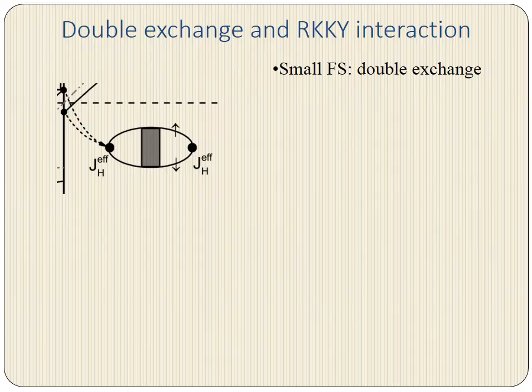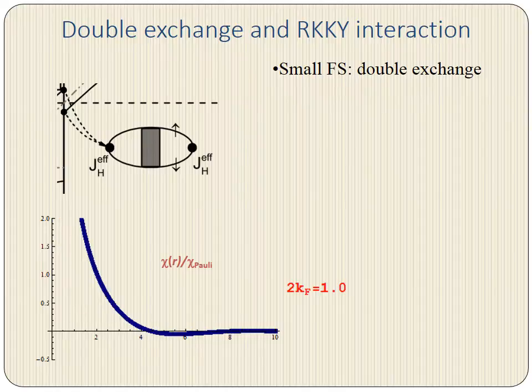Finally, I would like to briefly comment on how the interaction changes as the size of the Fermi surface changes. So up till now, we've been dealing with small dopings, which of course gives us small Fermi surfaces. In the context of this polarization diagram, we saw that this gave rise to double exchange. So what would happen if we increased the size of our Fermi surface? Well, the actual polarization diagram will not change. So what we'll do is we'll write down a simple toy model for this diagram, calculate the susceptibility, and see how it alters as the Fermi surface area is increased. And we end up with the following picture.